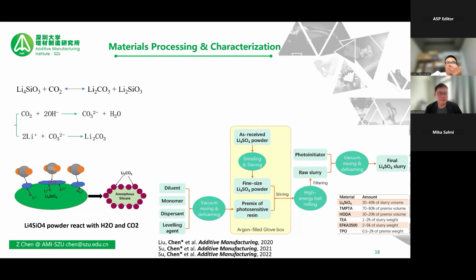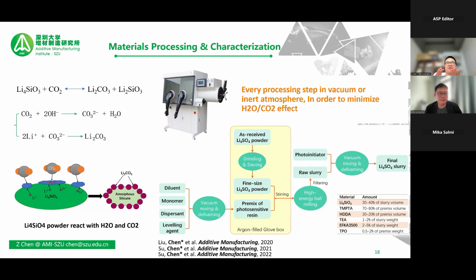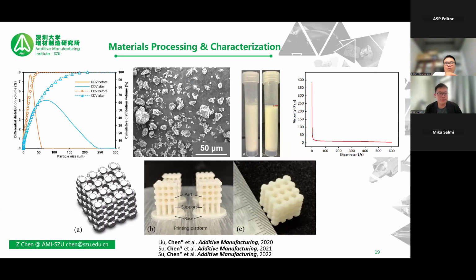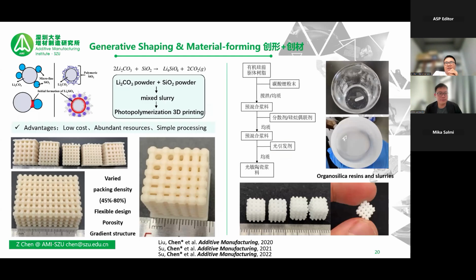to change the configuration, and we started to prepare our own slurries for the first time, because lithium orthosilicate is a very reactive material. It can react with CO2 and H2O in air. So we have to put all these material processing procedures inside an inert atmosphere, like a glove box, and then we produce our own slurries. It's similar to the previous case. Then we use photopolymerization 3D printing to print such a configuration, a structure which is no longer the pebble bed structure. We have a lattice structure here, and we tested some of the results, and they are much better than conventional pebble bed structures.